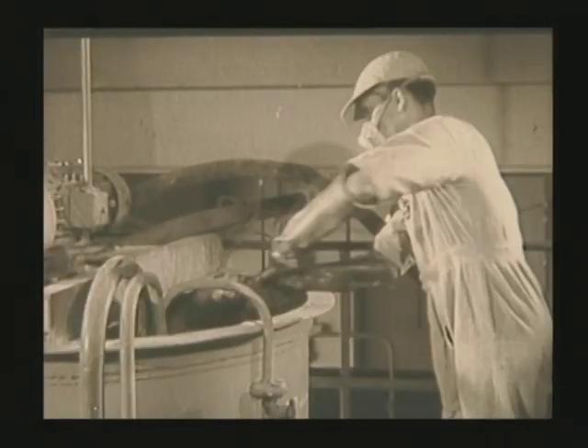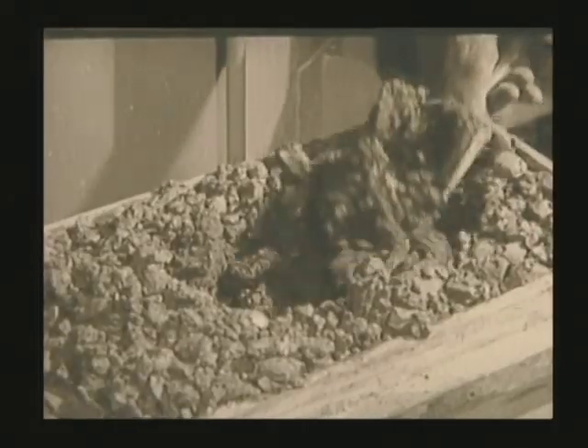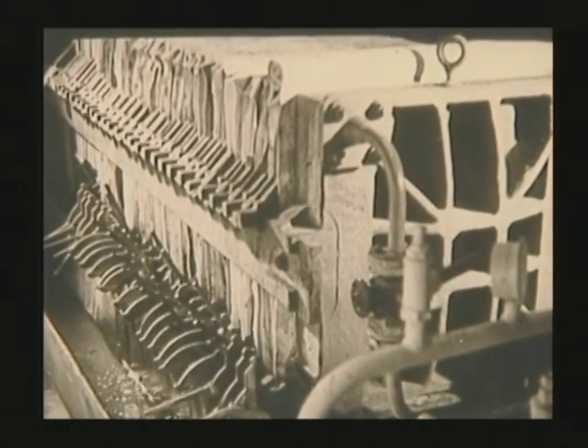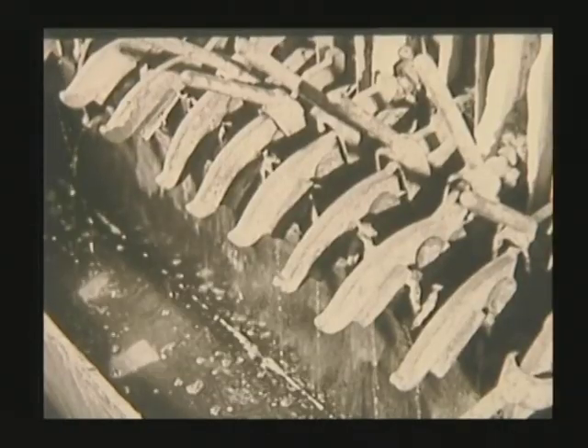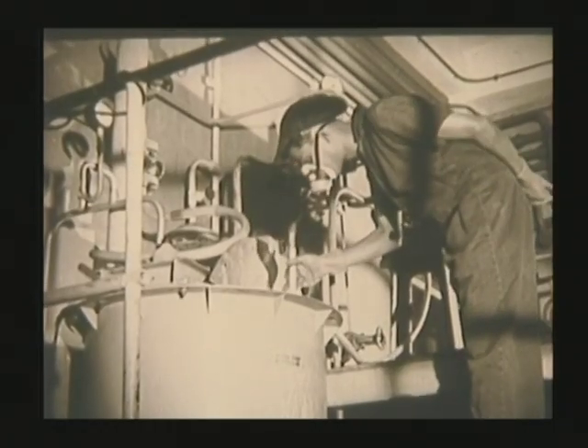The uranium fluoride obtained from the thorium plant is first treated with sodium carbonate and hydrogen peroxide. The resulting slurry is filtered, and the filtrate containing most of the uranium is treated with caustic soda. The uranium gets precipitated as sodium diuranate. It is then dissolved in nitric acid to obtain crude uranyl nitrate. This is purified by solvent extraction.